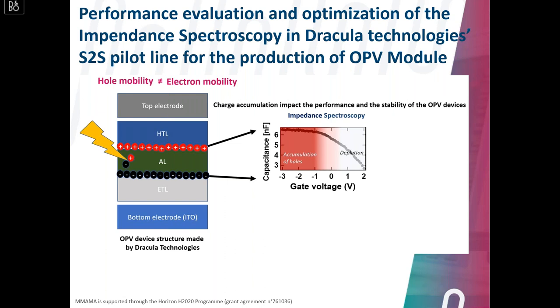It can be due to the bulk itself. Here, if we have, for example, again, the hole mobility different from the electron mobility, it can create some accumulation of charge at the interfaces. Then we can obtain a capacitance effect. And this capacitance effect will create an electric field, which can perturb, let's say, the transport inside the complete device, and of course degrade the performance of our devices. Such a technique can determine if we have this capacitance effect or not, and then we can even determine locally at which interface we can have this kind of phenomenon.